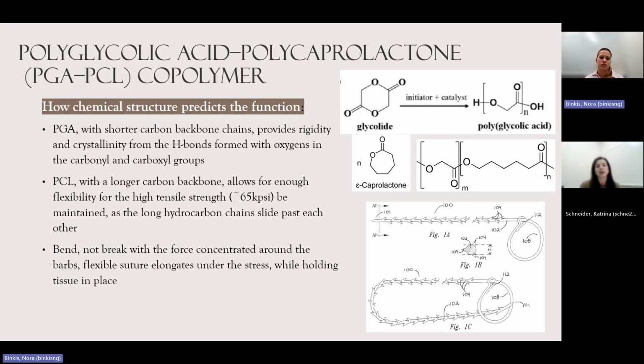The chemical structure predicts the function, as PGA has a shorter carbon backbone chain, providing rigidity and crystallinity from the hydrogen bonds formed with oxygen in the carbonyl and carboxyl groups. PCL, with a longer carbon backbone, allows for enough flexibility for the high tensile strength, about 65,000 psi, to be maintained as the long hydrocarbon chains slide past each other rather than shearing apart. It's designed to bend, not break, with the force concentrated around the barbs. Flexible suture elongates under stress while holding the tissue in place. You can see the loop structure in the bottom right.